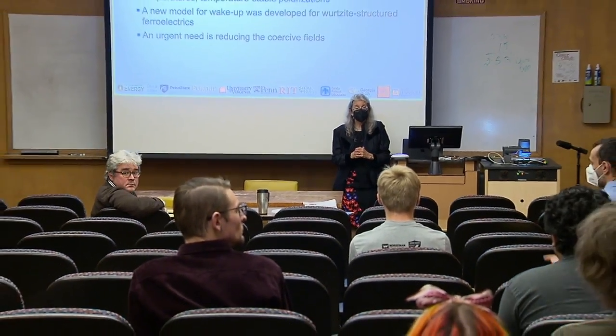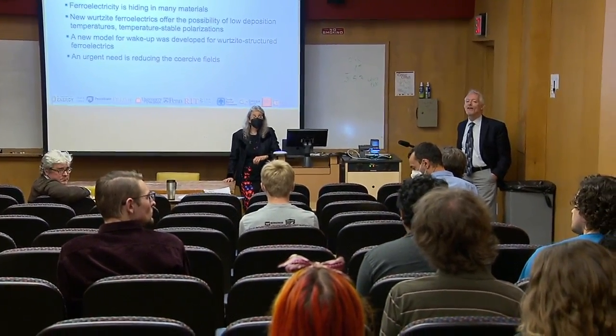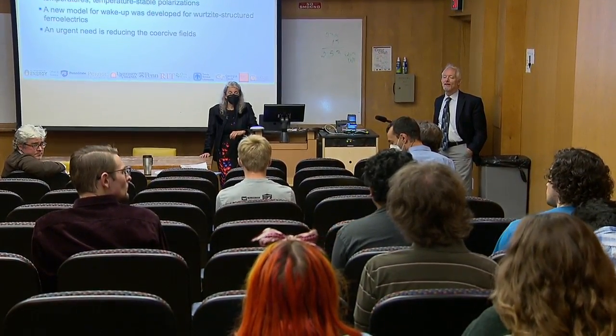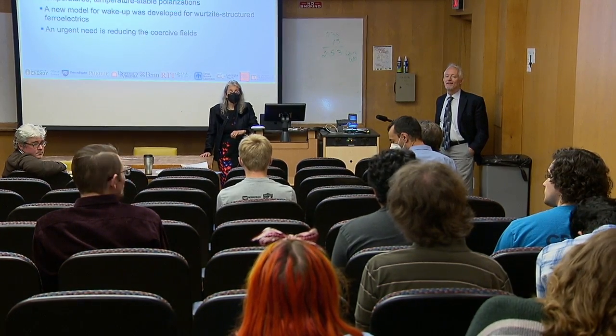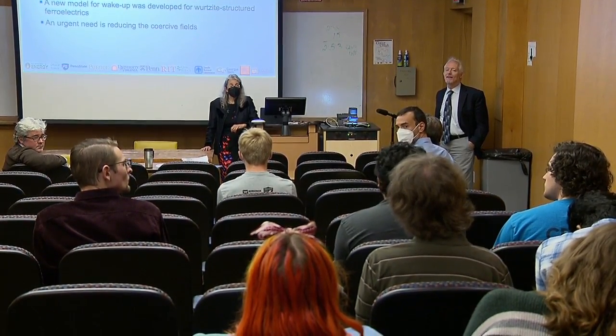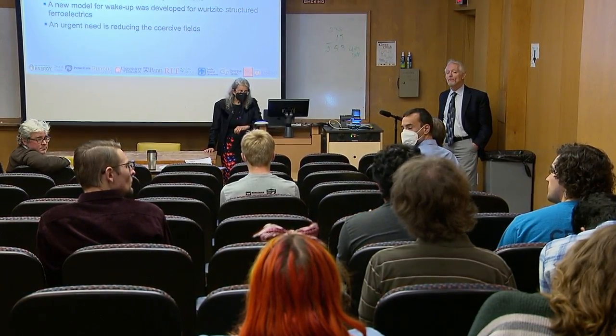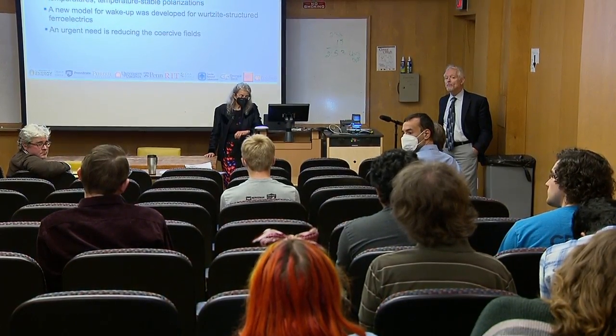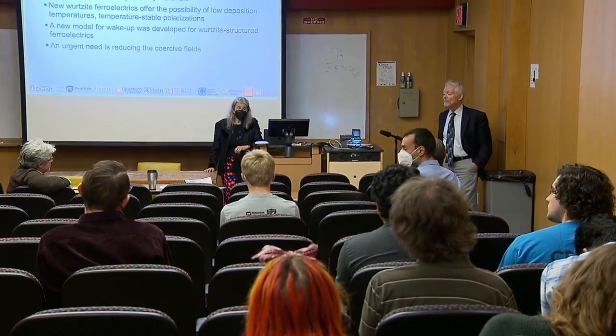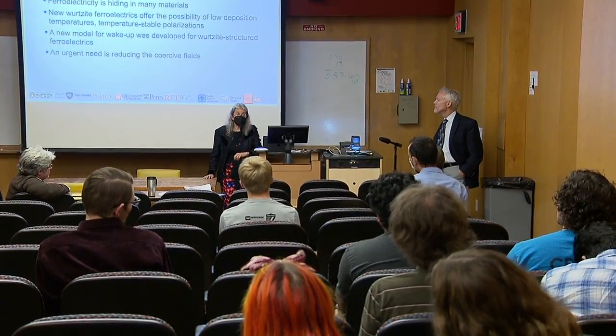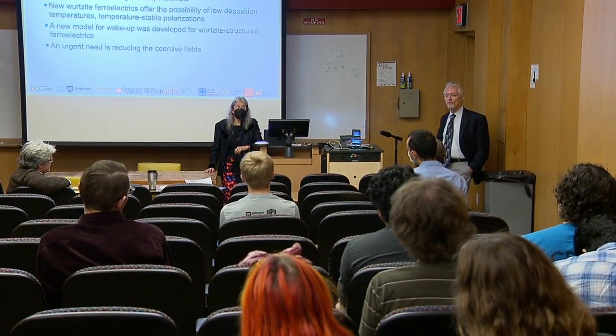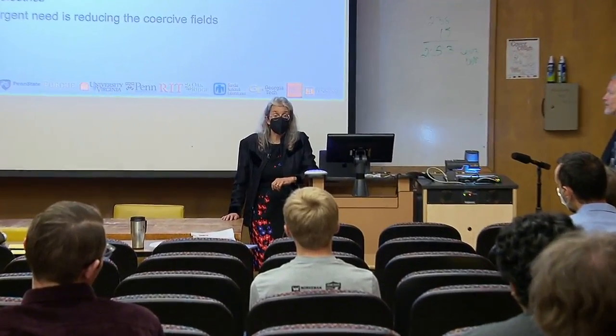Yes. You showed how the wake up makes the ferroelectric switching difference larger, right? So is there any aging effect, like any reversal, if you put it for a long time, does it stay steady? At room temperature, we have not found it yet. So we've woken up capacitors and gone back and looked at them months later, and they're still awake. We are now accumulating the data that says, can we put them back to sleep if we store them hot? And I don't have the answer for that yet.